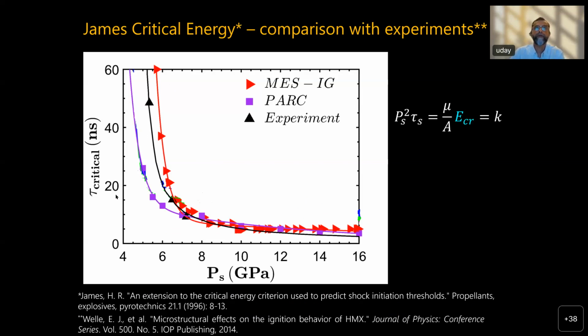The problem over here, and we're working on this, is that it's not truly hydrodynamic. The void collapse here. So there is also physics missing, I think, in this area of the plot. Because as you approach about 5 GPa and so on, you can get effects of shear bands and other strength-related aspects of the material. And those are not terribly well modeled currently in our work. We are trying to remedy that by using better physical models to represent the strength. And we made some progress on that, so that's ongoing work.